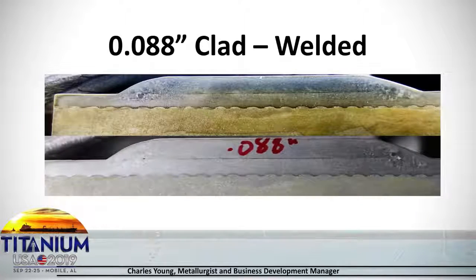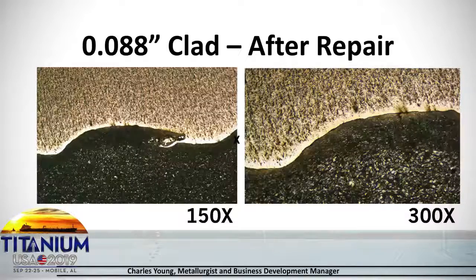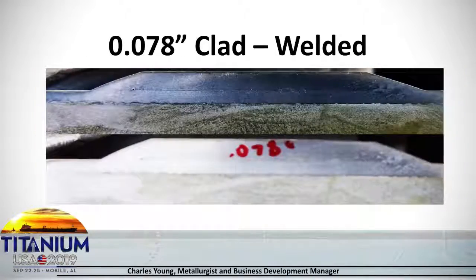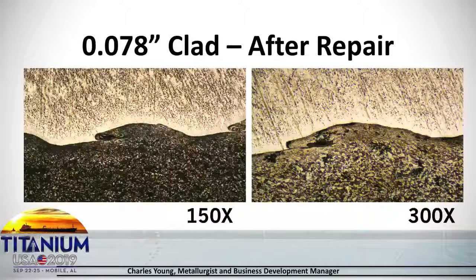Looking after repair at elevated metallographic samples, you can see that there's a very good weld repair there. No problems, no issues at the interface between the steel and the titanium. Looking at 0.088, you can also see here's the weld repair area on both sides. And again, you see no real influence at the titanium to steel interface here. So at 0.088, you'd still have a good weld repair. And again, looking at it under a metallographic analysis at 150 and 300, you again see there's no influence at the titanium to steel interface.